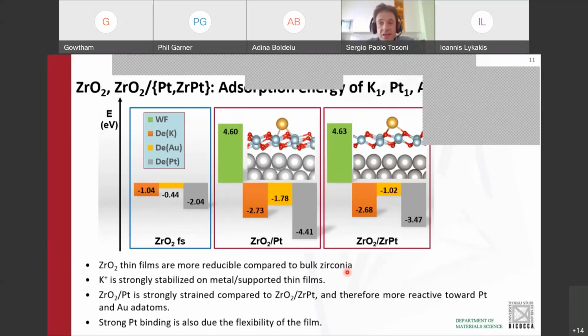Zirconia as a bulk oxide is a non-reducible oxide, while it is much more reducible in the form of a thin film. And this influences in a way its adsorption properties. For instance, potassium becomes potassium plus, and it is strongly bound on that type of film. And in general, zirconia on platinum seems to be more reactive toward all atomic species compared to zirconia supported on